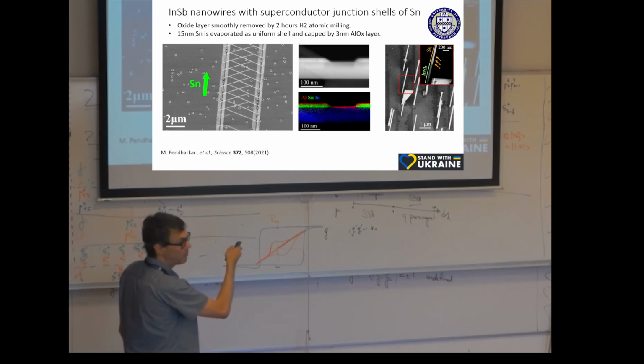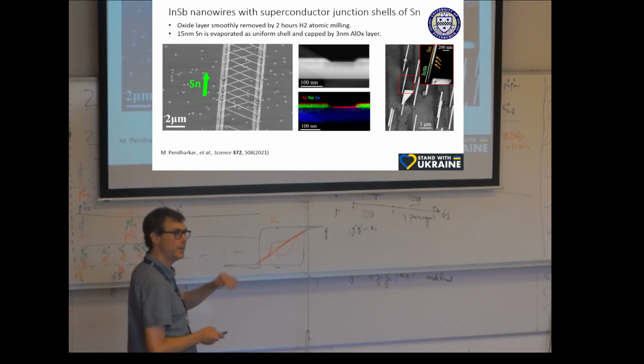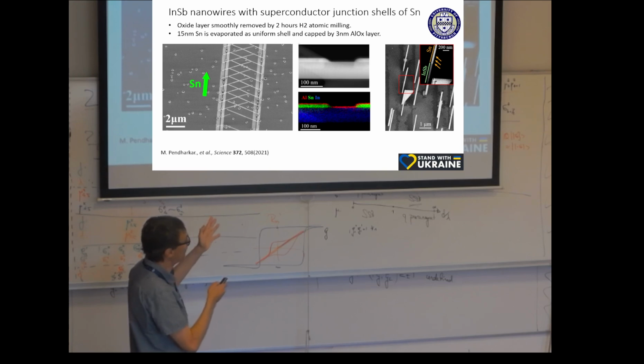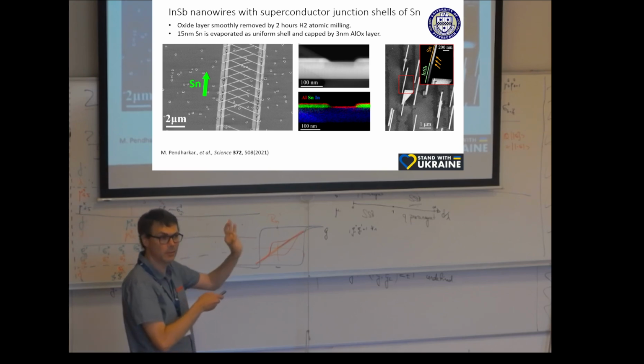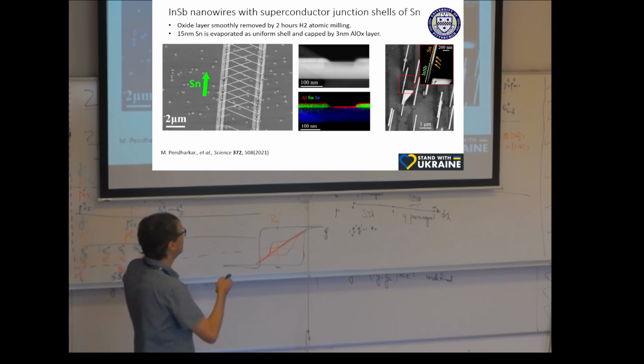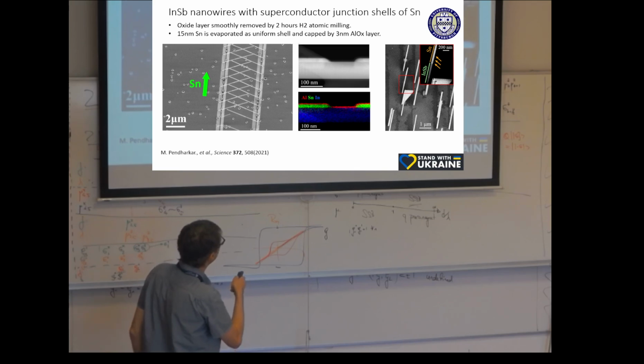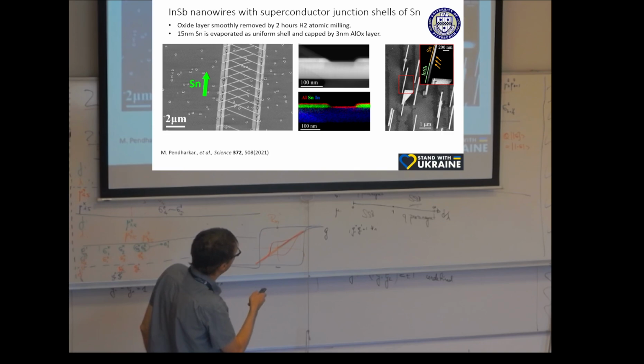The surface can have some roughness. And you know, when we get into the Majorana business with these, they're so beautiful and so elaborate, but they're still not good enough for Majorana. But for this stuff, it's pretty good. Right? So it's also capped with aluminum oxide to prevent this tin from oxidizing. This is another idea where there is a flake that shadows the wire.